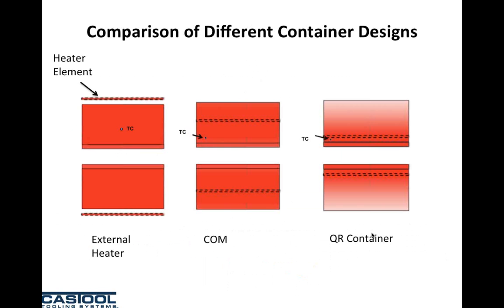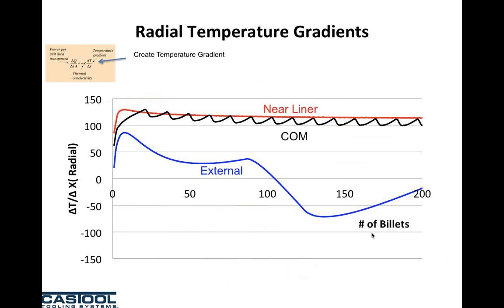The first one on your left, you see the heater is on the outside, and the thermocouple is in the middle of the container. In the middle one, you see the container is red, it's hot. On the right side, you see the temperature close to the liner is the extrusion temperature, but in the outer shell, the container is colder. So what would that do to your temperature gradient, which is the first component we talked about?